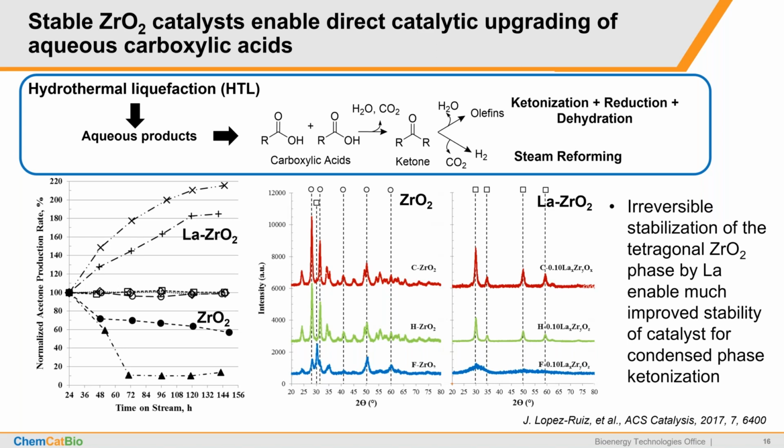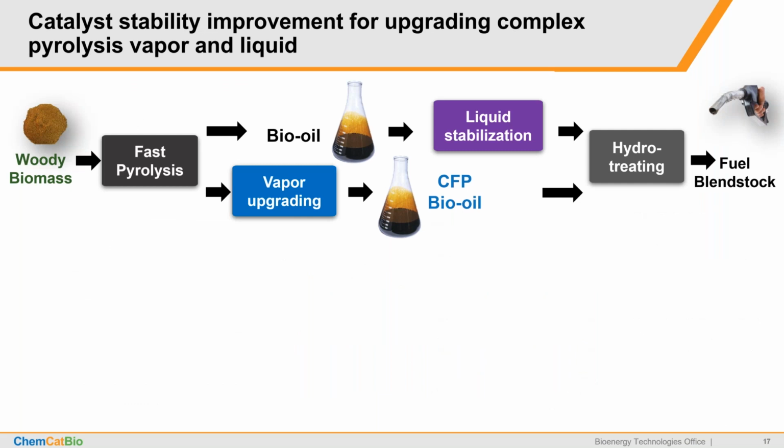By that, this catalyst was demonstrated more than 1,000 hours lifetime for this application, and this is reported in the paper I cited over here. I think I showed you that we do have a lot of nice studies to understand how we can mitigate this deactivation brought by condensed water reaction.